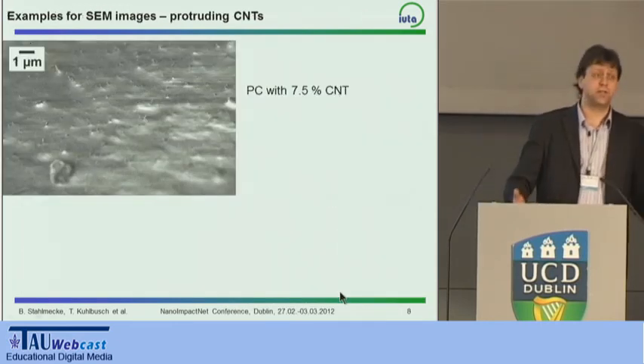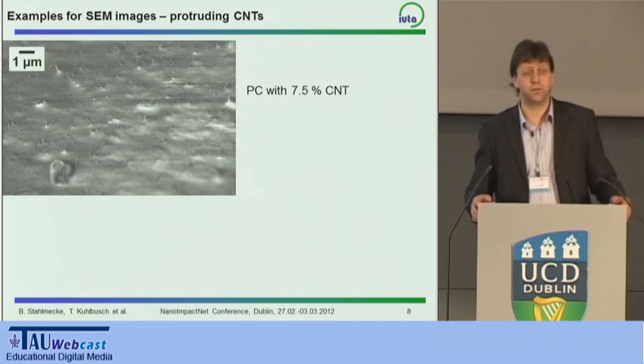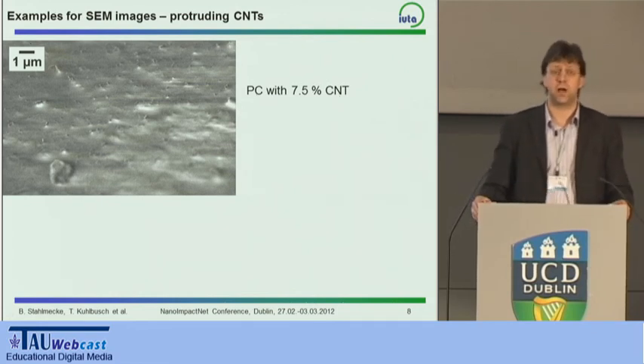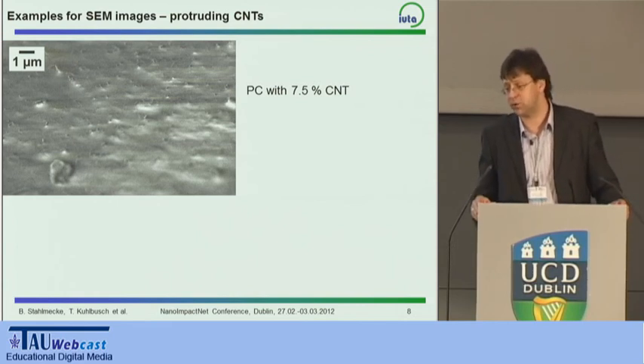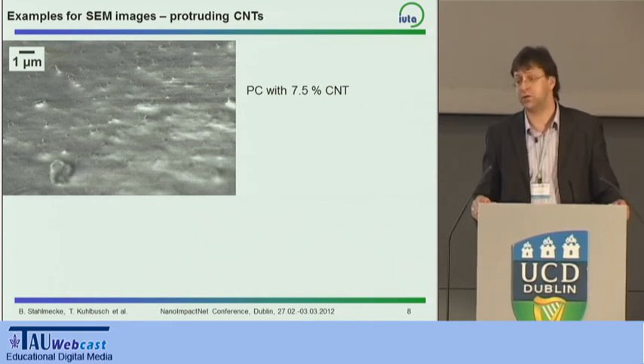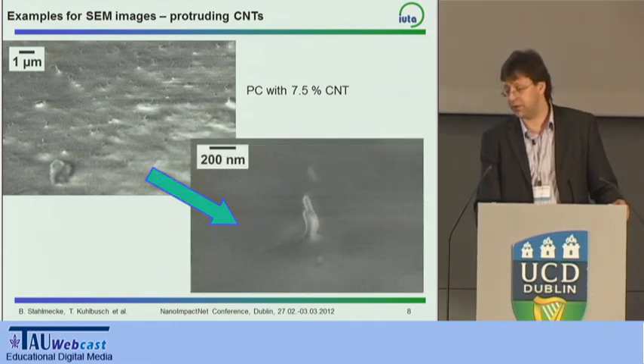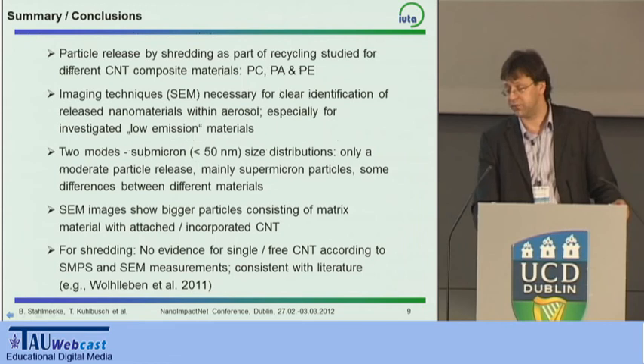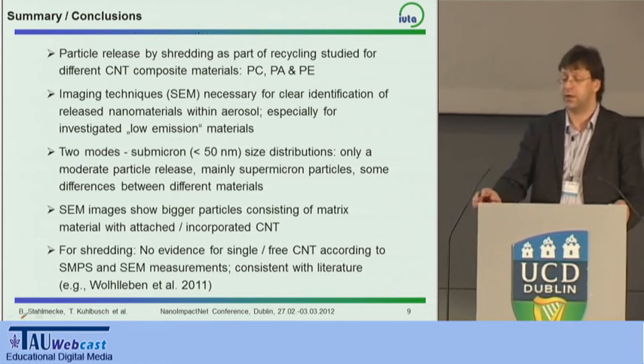When we went into details, even though we were looking for single carbon nanotubes, we couldn't identify any really single carbon nanotubes. What we frequently saw on the materials we were looking at was this type of picture where we can see here that we have different fibers coming out of the surface, which could be detected in this case for the 7.5% carbon nanotubes added.